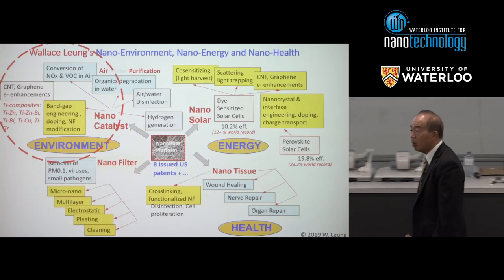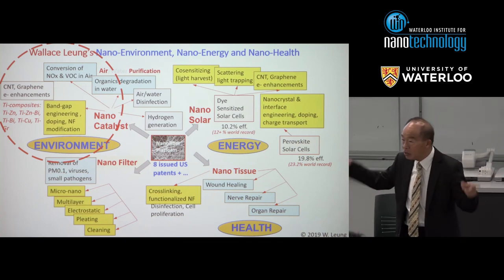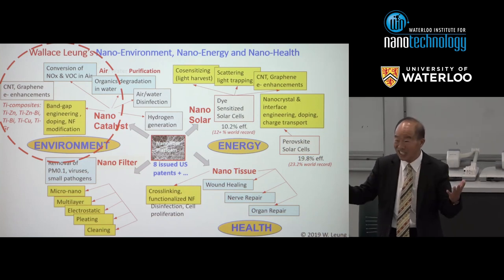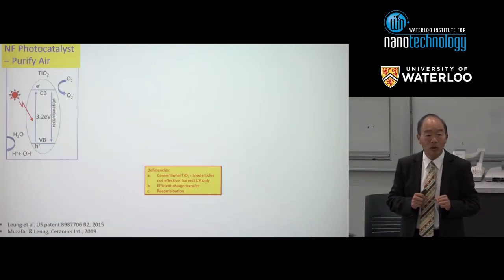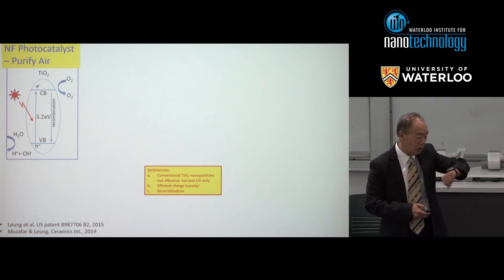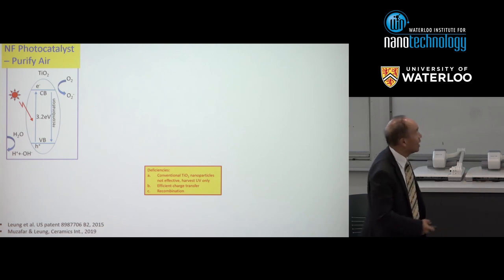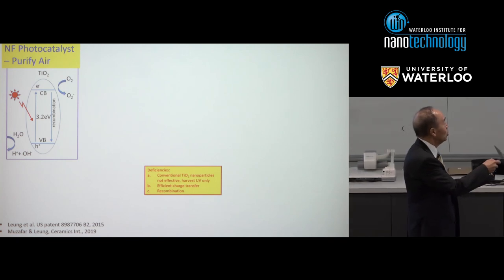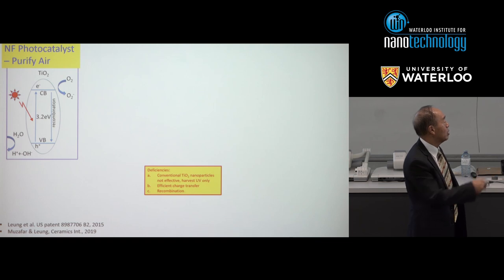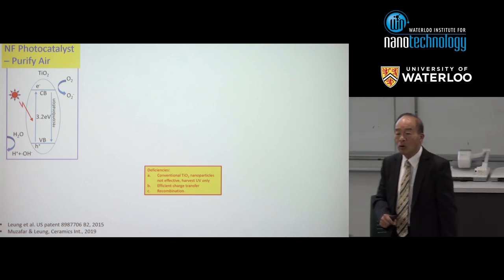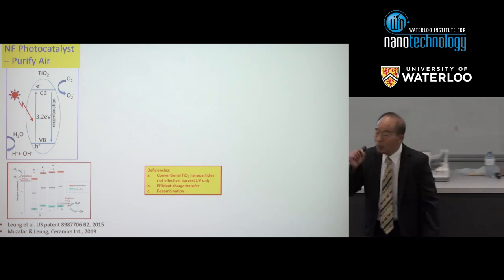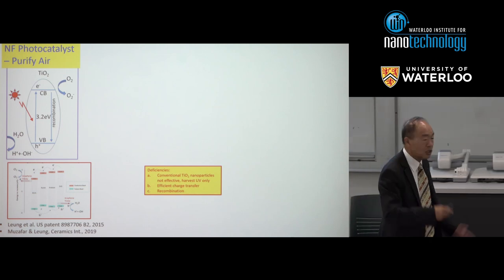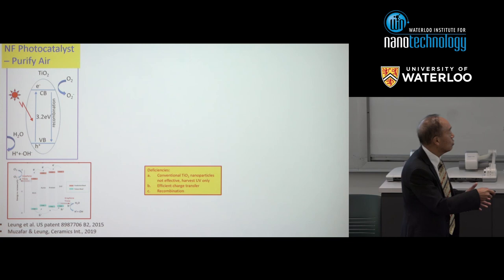The next topic is harmful gas. In this room there's formaldehyde and other VOCs — even perfume is a VOC. Back to basics: photocatalysis. TiO2 has a band gap of 3.2 electron volts. Under sunlight, an electron gets excited to the conduction band; the electron combines with oxygen to form superoxide, while the hole combines with water vapor to form the hydroxyl radical. However, TiO2 only harvests UV light, which is only 5% of the entire spectrum. So we add small amounts of other semiconductors — bismuth, zinc, etc. — to create additional energy barriers that separate electron and hole and extend the response to visible light.